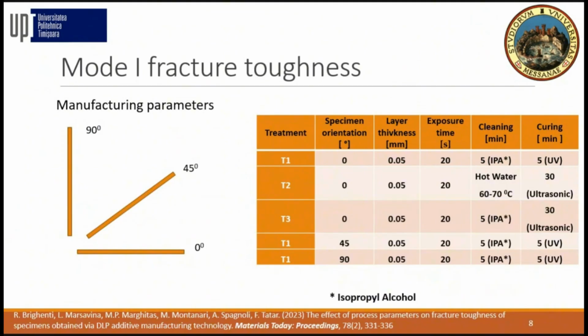Going to the mode 1 fracture toughness results. Here we consider 3 post-treatment regimes: 5 minutes cleaning in isopropyl alcohol and 5 minutes exposure to ultraviolet light; cleaning in hot water, 60 to 70 degrees Celsius, and ultrasonic curing; and 5 minutes cleaning in isopropyl alcohol and ultrasonic curing. Then we keep the first treatment, because this gives the best results on fracture toughness: 5 minutes in isopropyl alcohol and curing for 5 minutes in ultraviolet light, and we change the position of the specimens, 0 degree in plane of the vat, then 90 degree perpendicular, and 45 degree.